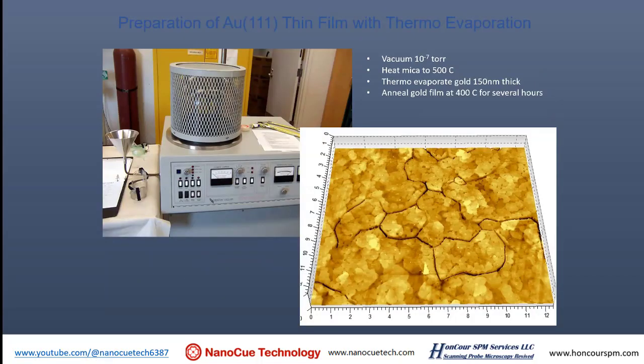Okay, so on the left corner is the device that people use to make a thin film of gold 111. Basically, it is an evaporator. It's a vacuum of 10 to the negative 7. And then mica is heated at 500 degrees C. You have a boat made of tungsten, and you pass a high current, so the boat is red hot. And you put some gold slug into that boat. And then the gold will melt.